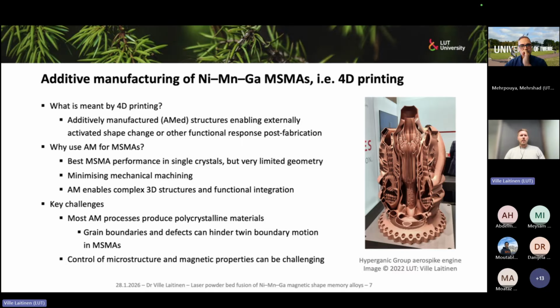The second thing is that, of course, we want to minimize mechanical machining in these production phases, because nickel, manganese, gallium in particular is a very, very brittle material. And also, because of this really low twinning stress that allows the magnetic shape memory effect to occur, it also deforms very easily in martensitic form. So it's very difficult to cut it into a shape.